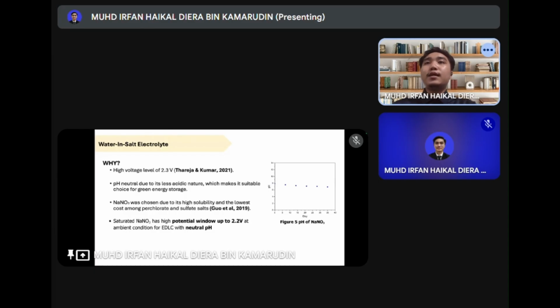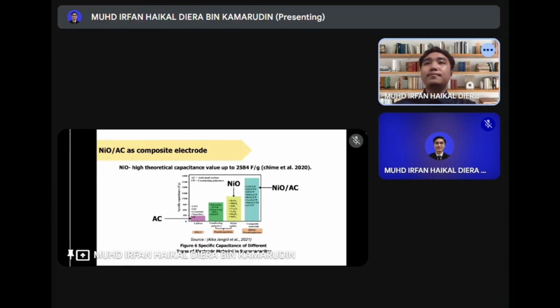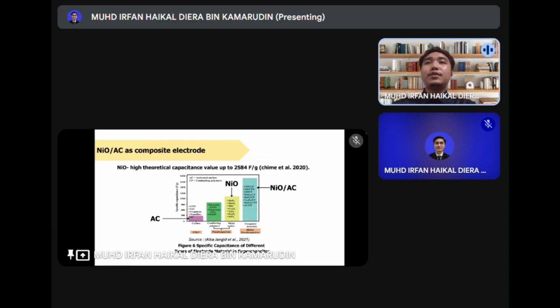Next, let's talk about the electrolyte, another key innovation in our supercapacitor design. We use a water-in-salt electrolyte, sodium nitrate, NaNO3. This system offers a high electrochemical stability window up to 2.2 volts under ambient condition. This is a significant improvement compared to conventional aqueous electrolytes. It is also neutral in pH and is the most cost-effective option, making it viable for scalable application. It also has an excellent balance of safety, performance, and affordability, all while supporting sustainable development. In this study, we also use NiO in addition with AC, and it became a hybrid supercapacitor. The reason why we use NiO is because it has a high theoretical capacitance value of up to 2584 F/g.